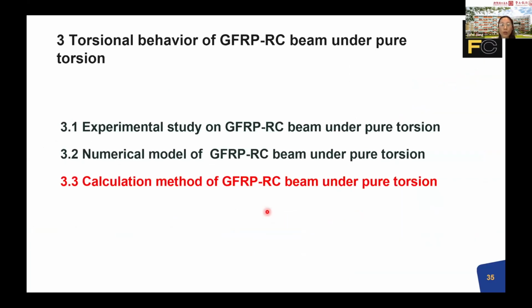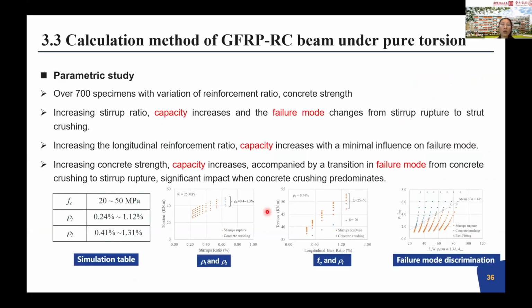Based on the numerical model, we also did a lot of parametric studies, over 700 beams under pure torsion, involving different reinforcement ratios and different concrete strengths, and developed the features of how they influence the capacity, especially the balanced ratio, which is the boundary ratio between over-reinforcement and the stirrup rupture failure mode.